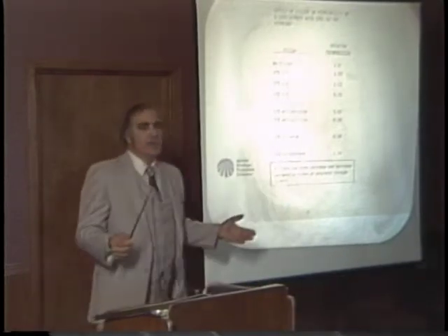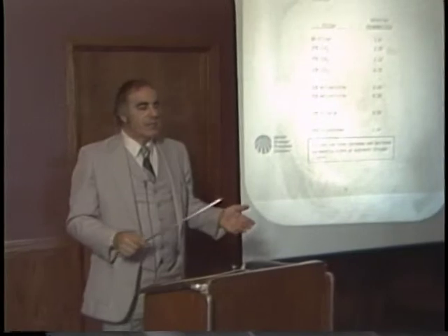Now here we see a polyimide filler, which is an organic filler. It tends to reduce it better than silica. And then we look at polystyrene, which even at the high level, the permeability is greater than no filler at all. So the message here is that fillers can both increase and decrease permeation rates of migrants through liners.